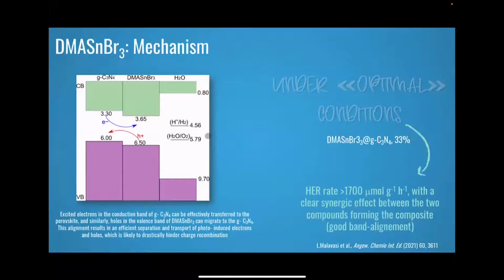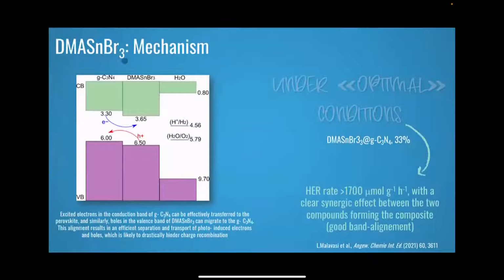So under the optimal condition, we could really achieve a hydrogen evolution rate greater than 1,700 micromoles of hydrogen. Okay, so thanks to this good band alignment. This was a quite nice result. Of course, to be honest, these are not, in any case, the most stable perovskites you would like to work with, because you then have a tendency of tin oxidation after the reaction. So it's anyway a complex system.